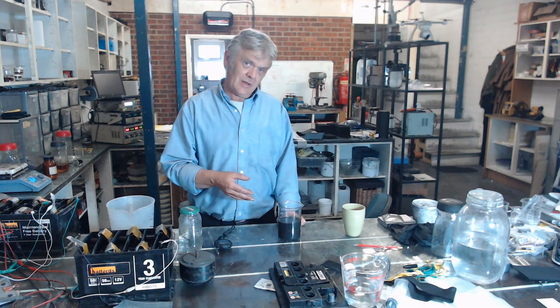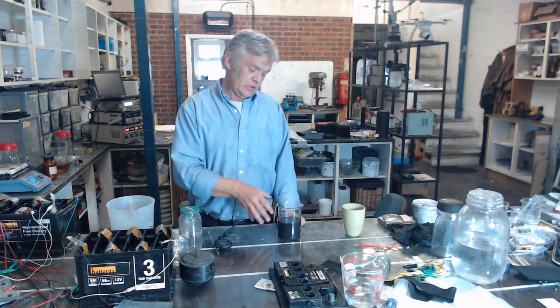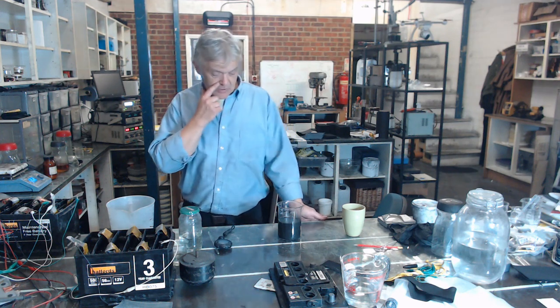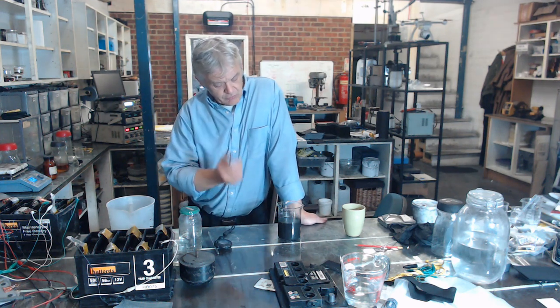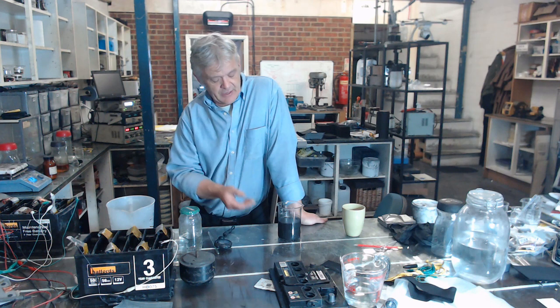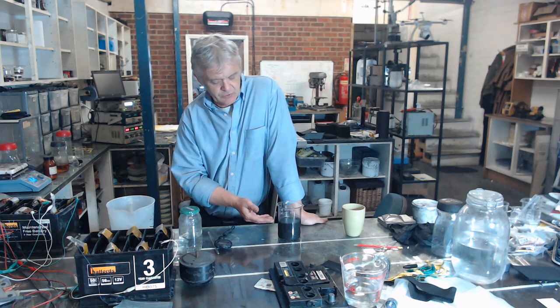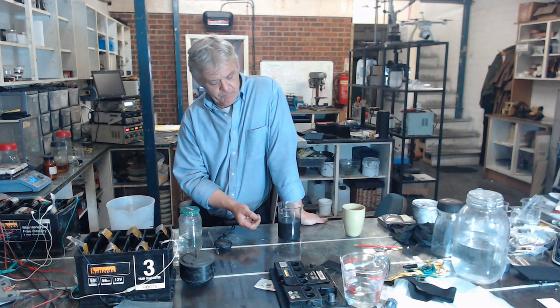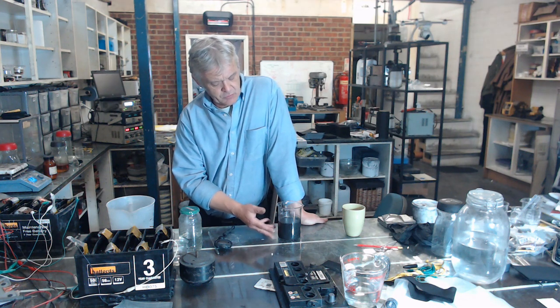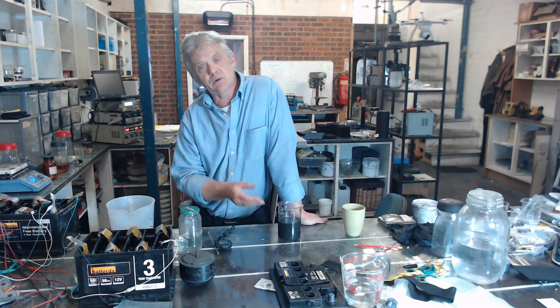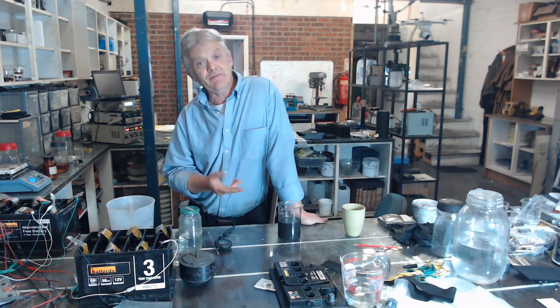But if we chucked that middlings in there, or the extra, or the fine graphite that we get, we chucked it into the solvent and stirred it, then the graphite would dissolve, if you like. Actually, it peels off as flakes, but it would dissolve in the solvent, and all the other stuff would drop to the bottom. As I say, once it's dropped to the bottom, you collect this stuff here and filter it, and what you get back is graphite.